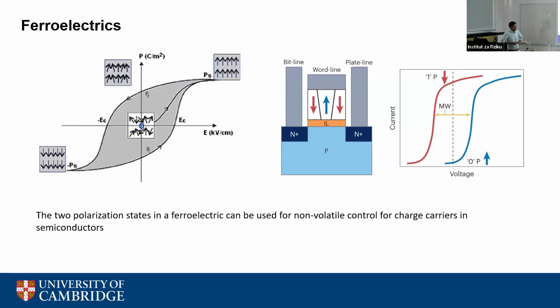Now, although this looks quite promising, there are a lot of problems, because ferroelectrics and their interfaces are always a huge problem when you look at the effects of ferroelectrics. The university has been working on ultra-thin ferroelectrics a lot as well. And as you reduce the thickness of these ferroelectrics, the interfaces play a huge role, and they can really change what you observe in your devices. So there have been hundreds of reports where you see loops, but all those loops don't mean ferroelectricity. They can be due to defects or traps or residues.